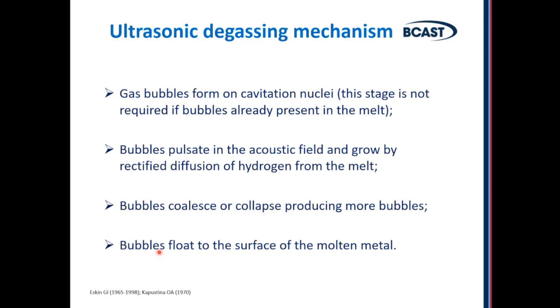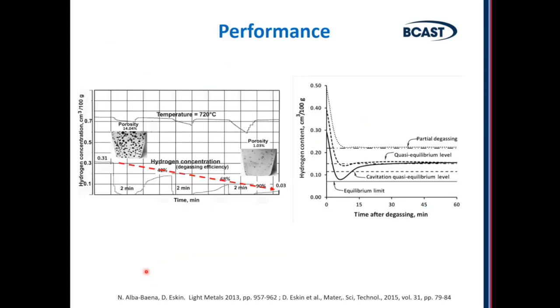mid-1920s for the degassing of liquid glass. Of course, in glass, degassing is important because you don't want to have glass with bubbles. But in application to liquid aluminium, it probably dates back to 1960s and still is a developing area with new equipment available. So the idea is that you create cavitation bubbles. They're filled during their pulsation with dissolved gases. Then they grow, absorbing more and more of dissolved gas, and then they float and release the gas into atmosphere. So this is degassing. It's very, very efficient.